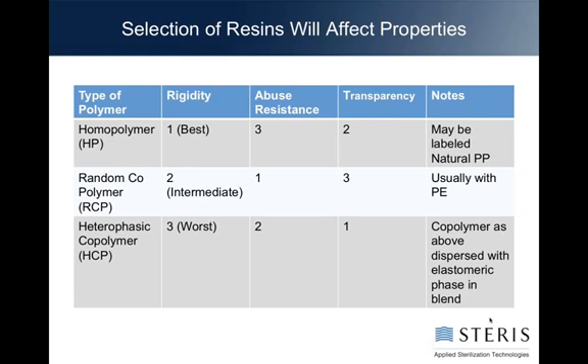A random copolymer, a little bit less on the rigidity. It's really good on the abuse profile and really bad in terms of transparency, so it'll be more opaque looking. A heterophasic copolymer is still a copolymer. It'll usually have dispersed into it an elastomeric, rubberized type of material that gives it additional properties. So it's not great on rigidity because it's got that elastomer in it. It's kind of in between on the abuse, but it's really good in transparency. So by adding additional types of things into that base homopolymer of polypropylene, you get some additional properties that can be actually quite rewarding.